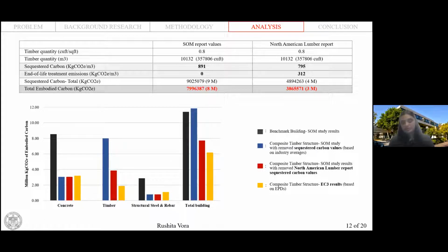For this assessment, two different carbon sequestration values were considered, one wherein the end of life treatment emissions were accounted for, and one where they were not. Now, when you use two different carbon sequestration values, the end results are distinctly different. This assessment again highlights that in the absence of information about the end of life treatment emissions and carbon sequestration, the use of a more conservative tool like the EC3 tool avoids misleading and inaccurate calculations.